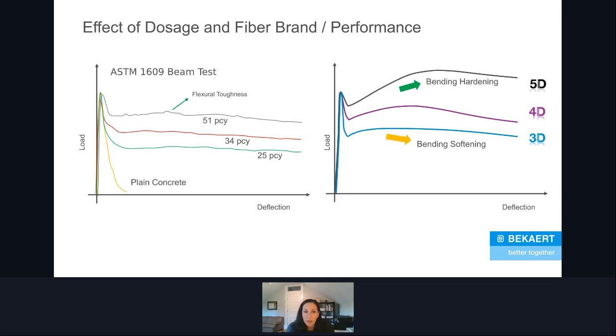I can't ignore the effect of the dosage and fiber brand and performance of any individual fiber. So essentially, it's very intuitive with dosage that the more you add, you'll have better post-crack flexural performance, right? If you take the same fiber and just add more of it, these are dosed in pounds per cubic yard. If you go from 25 to 34 to 51, right, your flexural toughness, your EFS, your RE3, all of those metrics are going to increase. Of course, there are consequences to that, right?